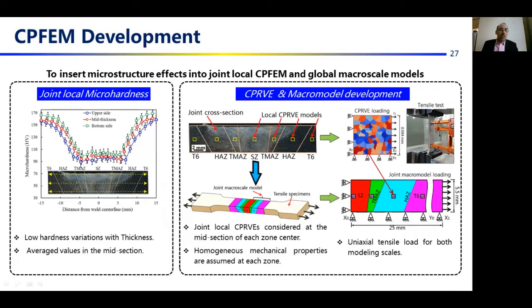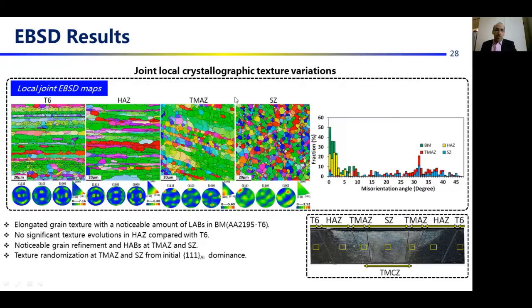For the CPFEM development, firstly, the micro-hardness test showed low variations in the mechanical properties through the thickness, and the average values can be seen in the midsection of the joint. So the joint local CPRVEs are considered at the midsection of each zone at the mid-thickness of the sheet, and homogeneous mechanical properties are assumed for each zone. It means the mechanical properties in the CPRVE model are assumed to be homogeneously distributed in the corresponding zone. And the tensile tests are simulated for both CPRVEs and the macro model of the joint to obtain the local and global tensile properties of the FSW joints.